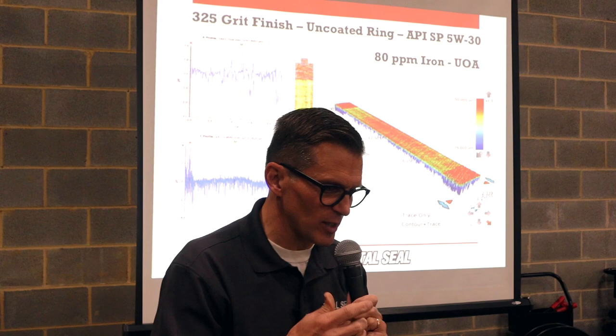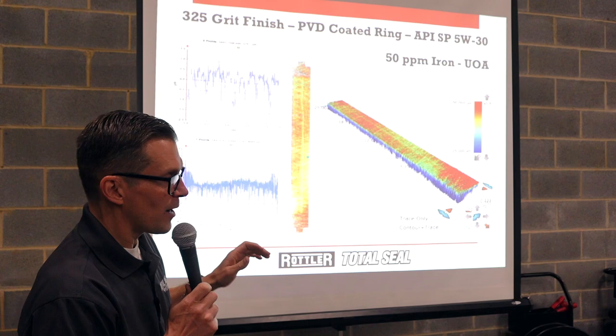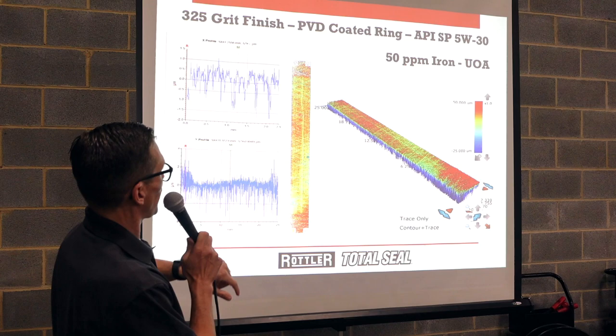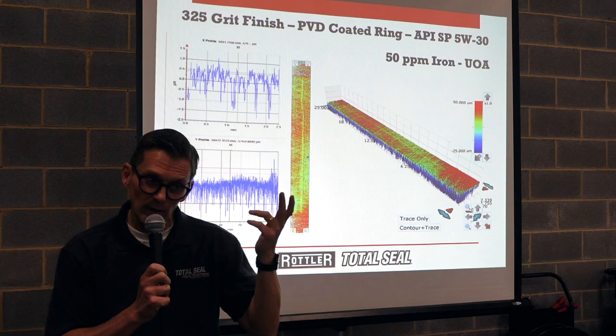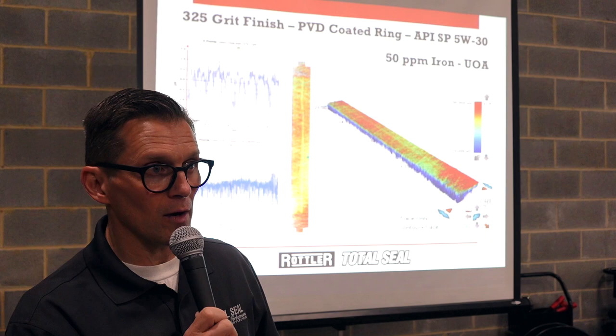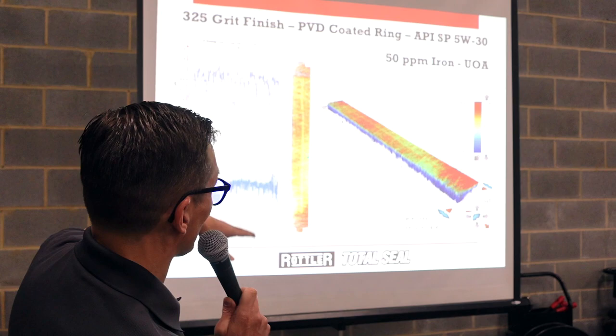Now we took the same thing and put a coated ring on it. And it instantly gets better, because now we're only at 50 parts per million iron. We got a little bit of debris dragging in there, which is one thing to remember. When you have those higher peaks, what's going to happen to them? They're going to get mowed down. So it's probably going to do more damage because they're dragging all around. But overall, the wear was still quite a bit less.